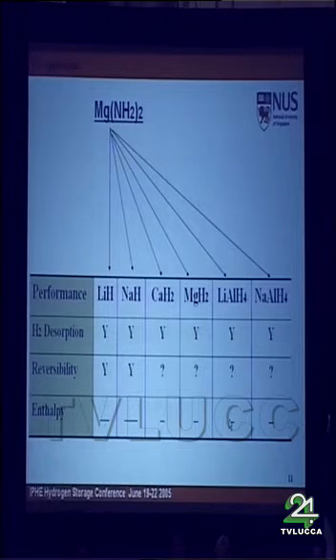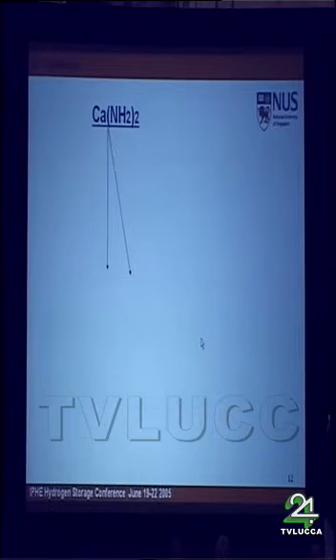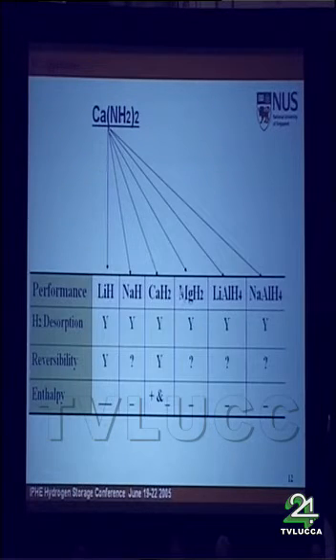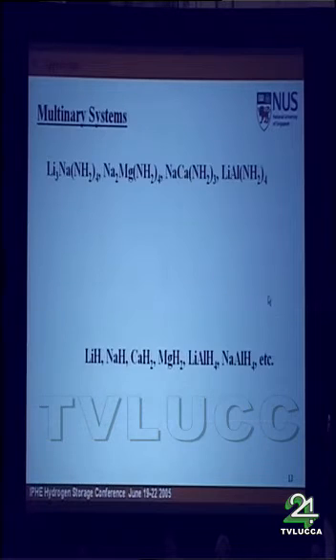Also, we can change the amide to magnesium amide and look at the chemical reactions between magnesium amide and different hydrides. You can see hydrogen can be generated even near room temperature. Here I just put no or yes. Actually, some of the hydrogen can be desorbed near ambient temperature. Some of them need high temperature. Also, we can use calcium amide to work with different hydrides, and we can also adopt different ternary amides and let them work with different hydrides.